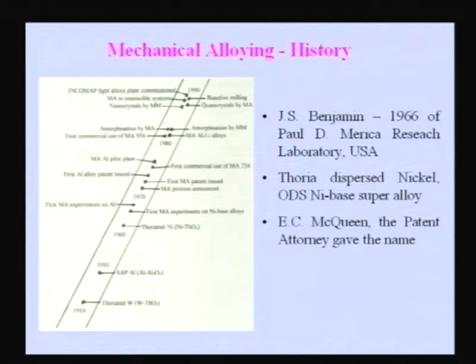Further reduction. So as a result, they thought they will use the ball mill to coat nickel on the thoria or on yttria. They were quite successful, and then they thought, why don't we straight away make the ODS nickel based superalloy. What is ODS? Oxide dispersion strengthened. That means yttria or alumina or thoria, any oxides. So you disperse the oxides into the nickel based superalloy.